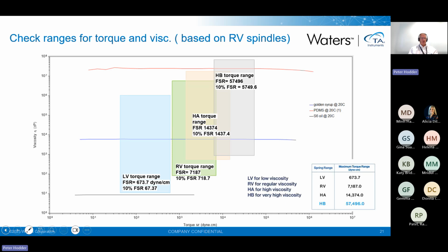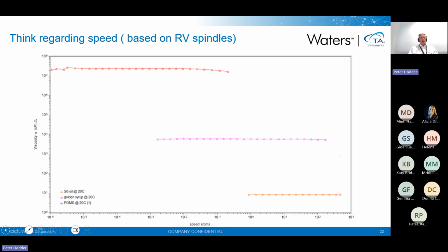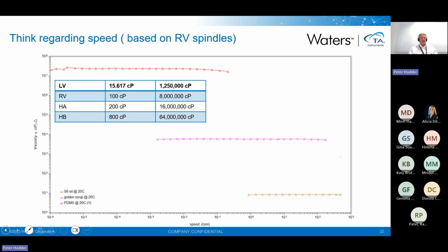However, we don't just talk about torque ranges. We talk about being able to change the spindles, but more importantly, the speeds. So I'm actually considering the speeds of these RV spindles. And on the bottom now, we've got RPMs, which is the typical speed setting for a Brookfield. What I put on here, if we look at the values, are the ranges we expect to be able to measure between the viscosities, again, reminder. But the speed range for an LV is there. And again, it clearly shows that we can measure the golden syrup, now in purple.